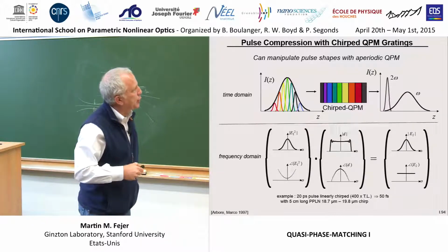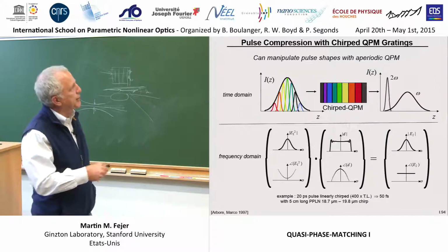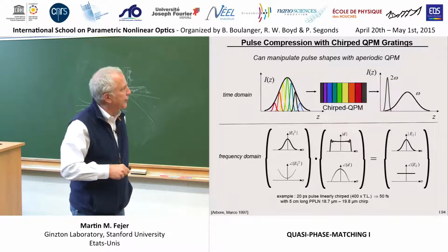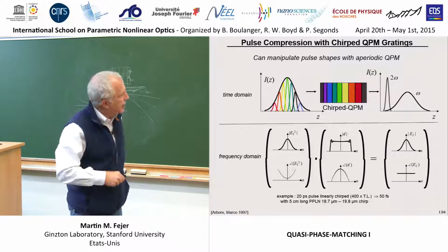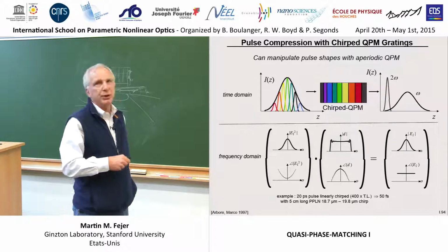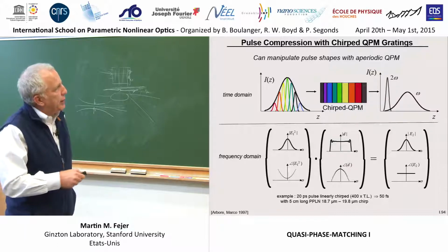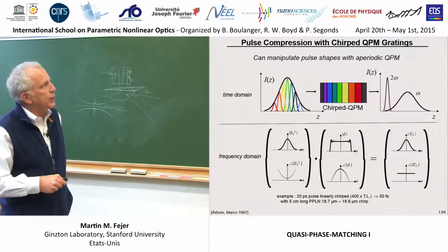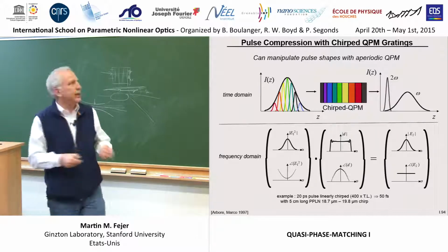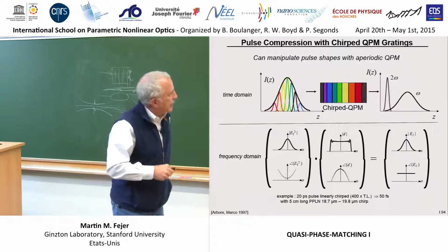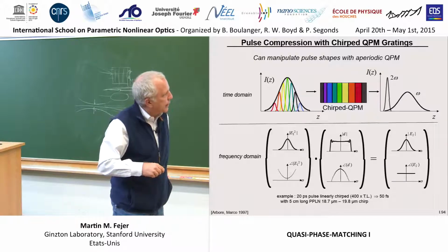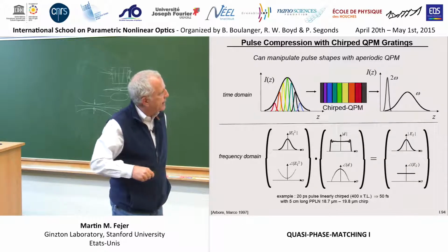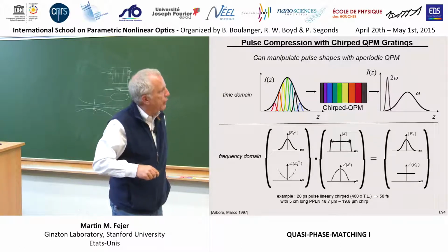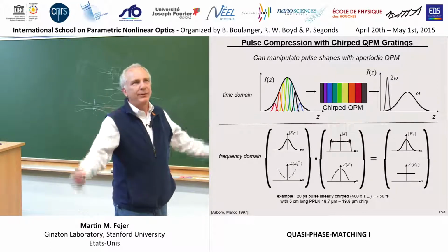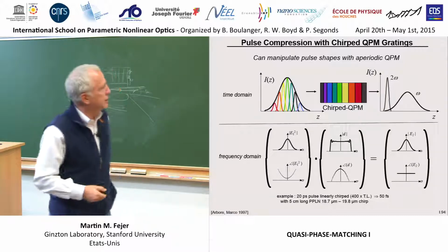If this were simply a linearly chirped grating, if we go back to our pulse, our pump pulse, it's, say, a Gaussian envelope as a function of frequency, and if it's a linear chirp, as we heard in some of our discussion of fiber optics earlier today, it's got a parabolic phase versus frequency. That's a linear frequency chirp, right? We put this into a chirped QPM grating, and we know that the transfer function of this QPM grating goes like the Fourier transform of this grating pattern. And if this is a simple linear chirp, it turns out that the Fourier transform of that is basically a flat top with some ripples on it in amplitude, and in phase, it's also parabolic in this mid-spectral region. The phase of a linearly chirped structure is quadratic versus frequency.